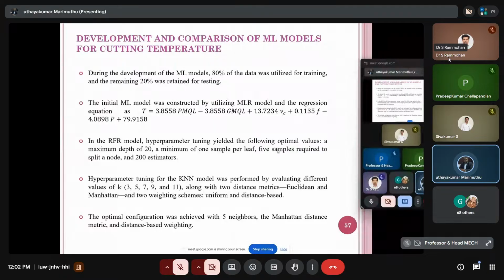In the RFR model, hyperparameter tuning yielded the following optimal values: a maximum depth of 20, a minimum of 1 sample per leaf, 5 samples required to split a node, and 200 estimators. The KNN model was performed by evaluating different values of K along with two distance metrics, Euclidean and Manhattan, and two weighting schemes, uniform and distance-based. The optimal configuration was achieved with 5 neighbors and so on, and the result is reported here.